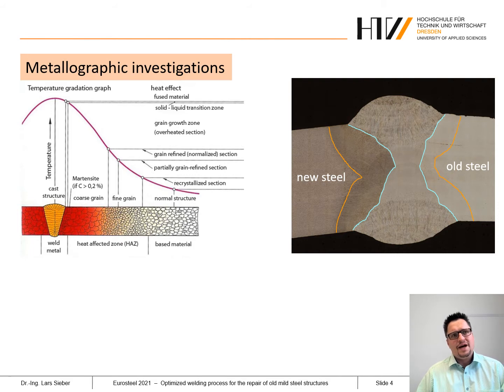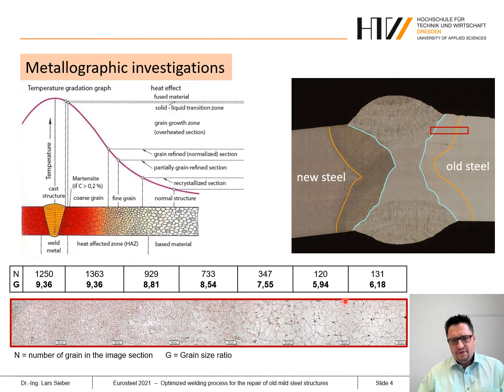On my last slide in Copenhagen, I also presented the reason, or first idea, for this higher strength and ductility in the heat affected zone. In metallographic investigations, we had found a continuous grain refinement, as you can see here, from the base material up to the welding line, without any coarse grain formation. We achieved this by limiting the thermal energy introduced during the welding, by using the basic electrodes, by performing these stringer beads, and so on. This made it possible to almost completely suppress the grain growth zone, which is typical for modern welding processes with a higher deposition rate.